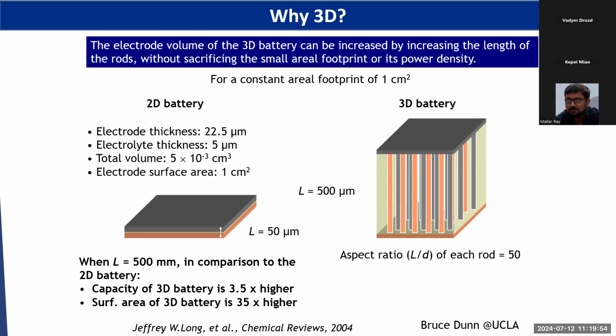So why the 3D concept? Let me give you a very quick, simple calculation. We borrowed this slide from Bruce Dunn at UCLA. This slide basically tells you very simple mathematics. We assume a thin film, 2D battery design compared to a 3D battery design at the same footprint area, 1 centimeter square in this case. And we assume the electrode thickness is 22.5 micrometers, and the electrolyte thickness is about 5 micrometers.